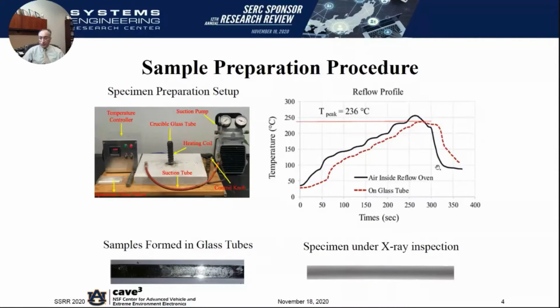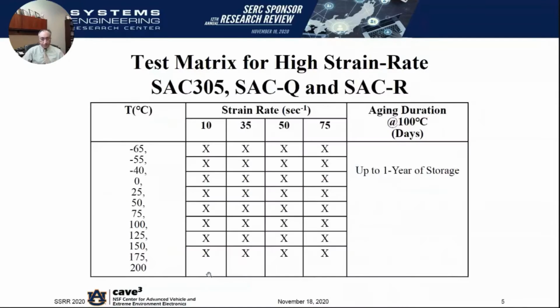This is a typical reflow profile that the specimen would go through. And once it's gone through reflow, to be able to replicate the grain and phase structure in an actual package, we would then X-ray it and make sure that the specimen is free of defects. And the idea is to create a thickness of the specimen that's about the same order of magnitude or similar in dimension to that of a package level solder joint. Although the width and length are larger, the thickness is very similar to that of an actual joint.